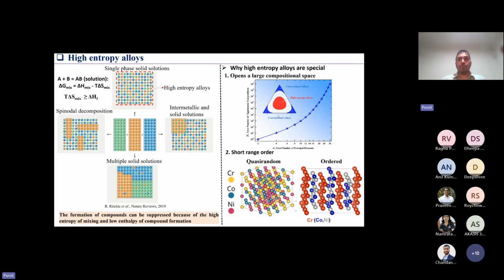The second example I want to give is the formation of short range order. So usually when you mix a lot of these elements, what you would assume is that you might have a quasi-random structure. For example, here I'm talking about chromium, cobalt, nickel. You would assume that chromium, cobalt, nickel will randomly choose the positions in the unit cell, but in reality, there is a possibility that some elements might like to sit next to each other, or some elements might dislike sitting next to each other. For example, in chromium, cobalt, nickel, people have done first principle calculations, and they suggest that chromium doesn't like to sit with another chromium atom, and then you can end up with these ordered structures where you have a layer of chromium, then a layer of cobalt, nickel, and this way you can have this small short range order, and the consequence of this short range order is huge.